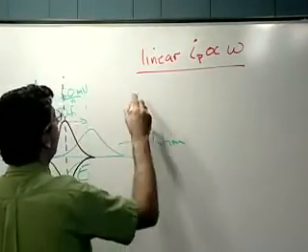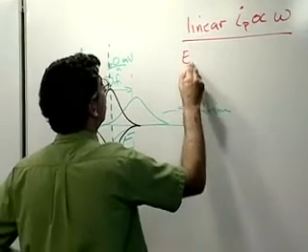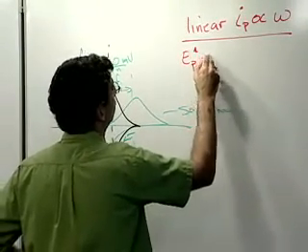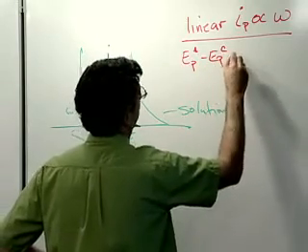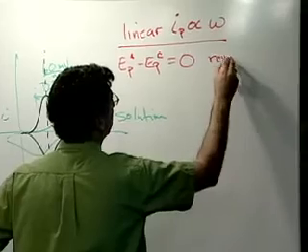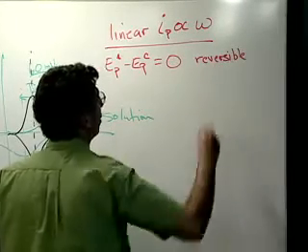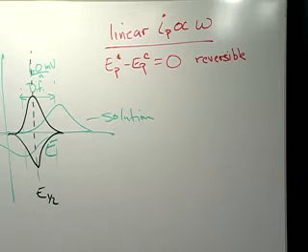We have now a peak anodic to peak cathodic dependence that is equal to 0 for a reversible process. I should point out that although you can think of lots of different kinetic schemes, EC, CE, irreversible and whatnot, on an electrode surface, when you have a chemically modified electrode, it's the reversible one that is the interesting one, because with anything else, you only have a chemically modified surface for one cyclic voltammetric scan. And after that, you've converted it into something else. So we are specifically interested in the reversible case here, so not working out the other cases is OK.